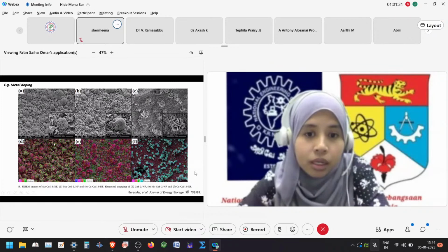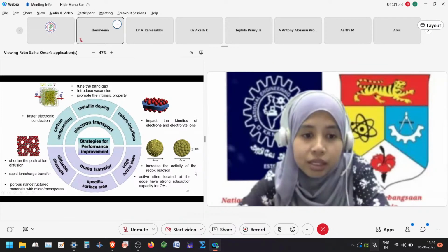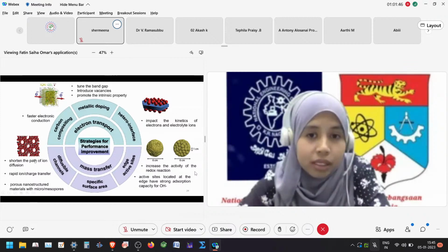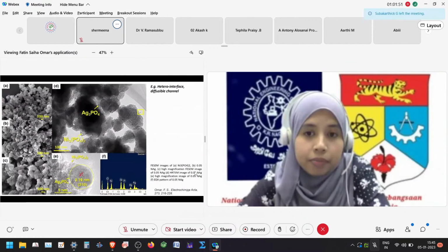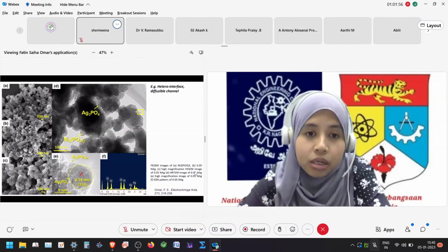And third, we can also introduce heterointerface, diffusible channels, and increase the specific surface area. For diffusible channels, it means that we can create pores in the electrode materials. So what we did in this work is we composite the amorphous structure of nickel phosphate and the crystalline structure of silver phosphate. This big particle is the nickel phosphate. If you see closely, this particle has a lot of pores.